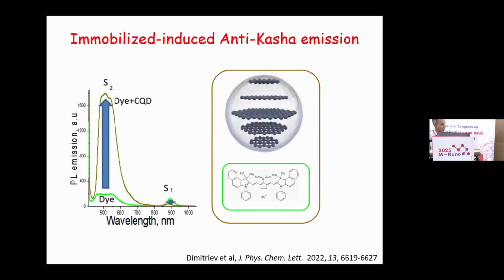And indeed, Anti-Kasha emission can be observed, as shown here by the green line, for these dyes in solution without any nanoparticles. We can see Kasha emission and Anti-Kasha emission. When we add carbon nanoparticles and realize the interaction of these infrared dyes with carbon nanoparticles, we can observe an enhancement of Anti-Kasha emission by about 1 order of magnitude. This is a very significant enhancement.